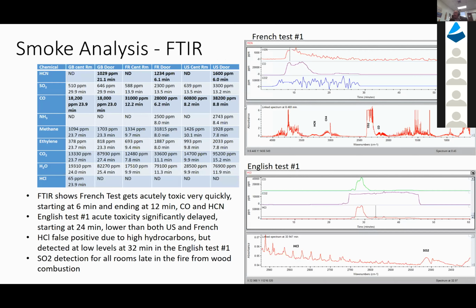Just looking at FTIR analysis of 2 locations within the room, we see very different performances of the French and here are the English room, the UK room are shown. You can see that you're extremely toxic in about 7 minutes for the French room. The carbon monoxide goes through the roof. Hydrogen cyanide is very high, whereas the toxicity of the UK room at the bottom sketch down there on the right-hand side, you can see that the toxicity of the smoke is much delayed. You're all the way out to 20 minutes before you see any toxicity at all in the smoke. So obviously it's much easier to escape. You have more time to do so. And the toxicities in the French are enough to be lethal with basically one breath knocking you down.